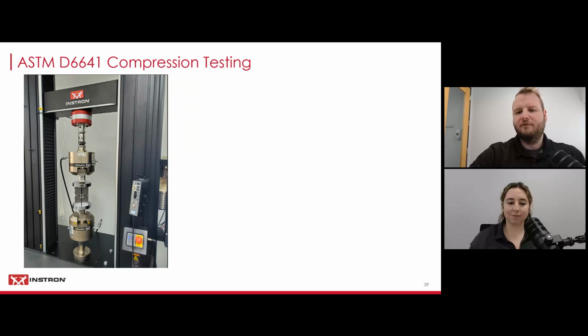Thank you, Ashley. Okay, now I would like to show you some of the compression testing that we've done in preparation for this webinar. The test method that I ran here is ASTM D6641, which seems to be one of the most popular composite compression testing standards from what we can tell here at Instron at least. This test method uses a combined loading approach, and that means that the forces are being introduced into the specimen via shear loading and also via end loading at the same time.